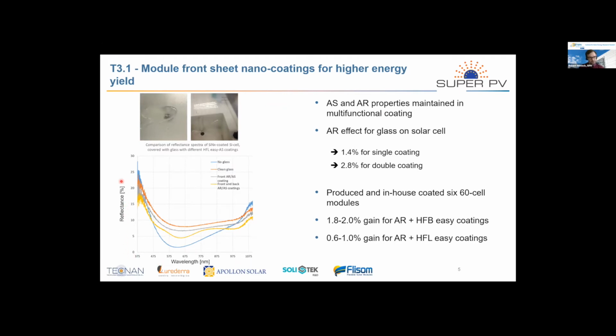This one in this case shows the reflection as a function of the wavelengths of the solar cell. So the blue data shows the bare solar cell without any glass. The red data shows the reflection with the untreated glass at the front side. And then we have two possibilities here. We have the gray data showing a single coating at the front side of the glass, which reduces the reflection by about 1.4%. And then we also have the possibility to have multilayer coatings. Here we have a double coating, which further reduces the reflection. And here we have a reduction in reflection of 2.8%.